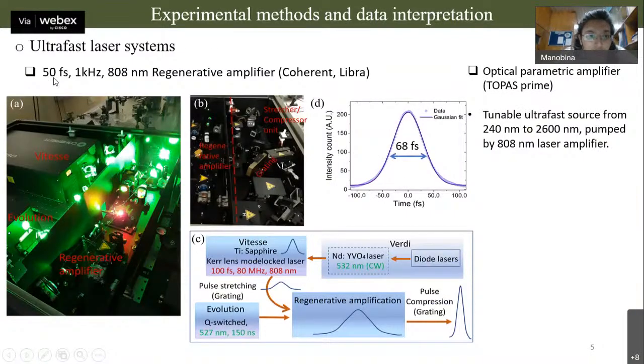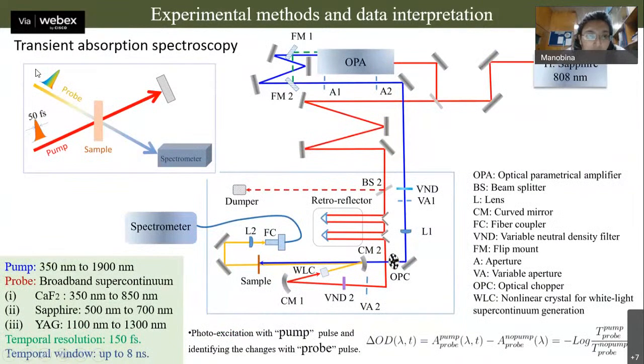We use a 50 femtosecond, 1 kilohertz, 800 nanometer regenerative amplifier as our master laser. And we use an optical parametric amplifier, where we get tunable output from 240 nanometers to 2.6 micron. As an experimental tool, we use transient absorption spectroscopy. As we know, this is a 2-beam technique where we excite the material with a pump pulse, and we observe the absorption with a weak probe pulse that comes after the pump at several delays, and we detect it in the spectrometer.